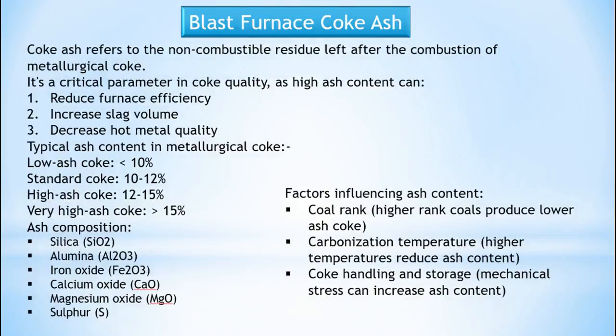Coke ash. Coke ash refers to the non-combustible residue left after the combustion of metallurgical coke. It is a critical parameter as high ash content can reduce furnace efficiency, increase slag volume, and decrease hot metal quality. Typical ash content: low ash coke less than 10%, standard coke 10–12%, high ash coke 12–15%, very high ash coke greater than 15%. Ash composition includes: silica (SiO₂), alumina (Al₂O₃), iron oxide (Fe₂O₃), calcium oxide (CaO), magnesium oxide (MgO), and sulfur (S).